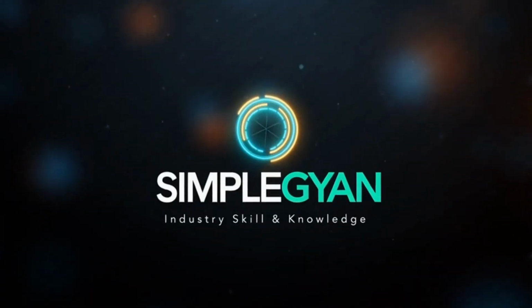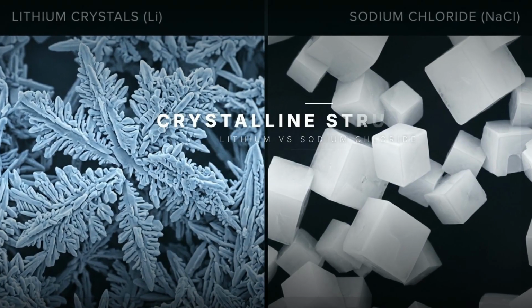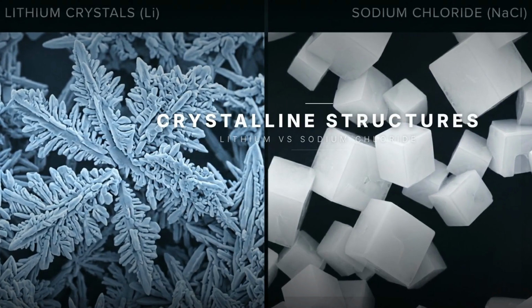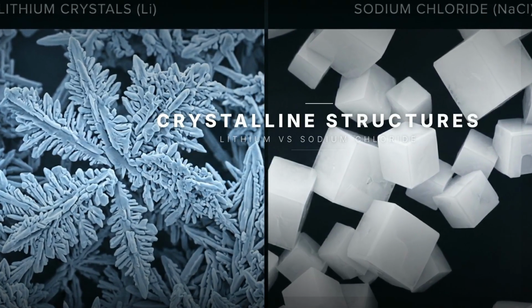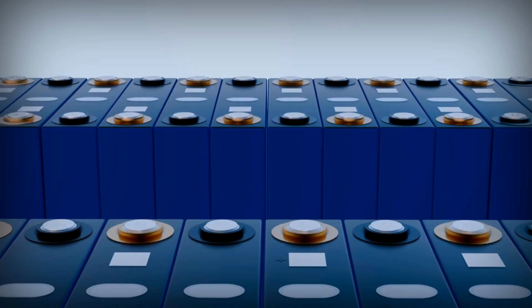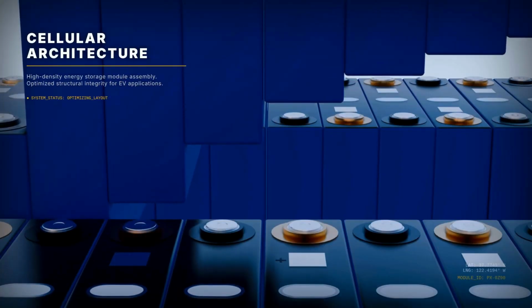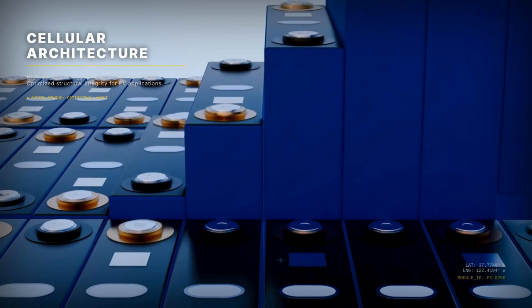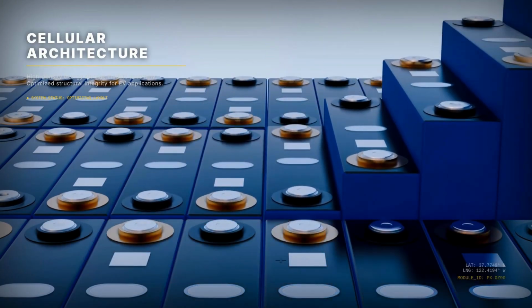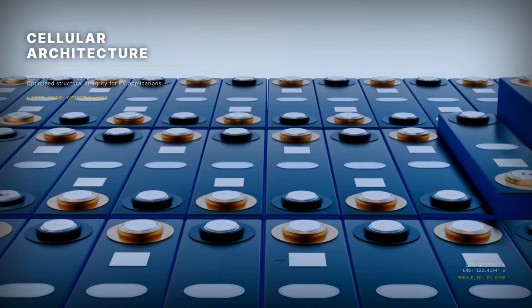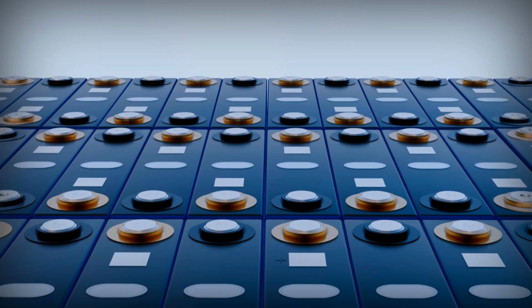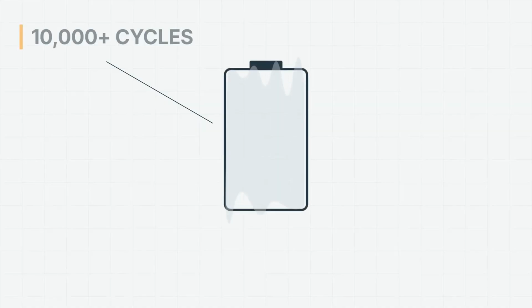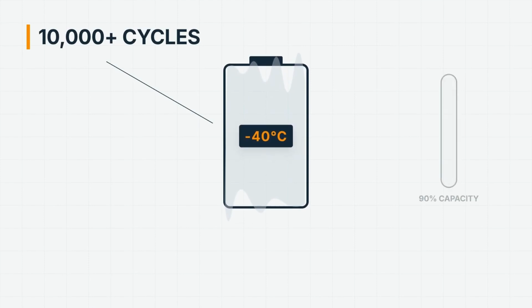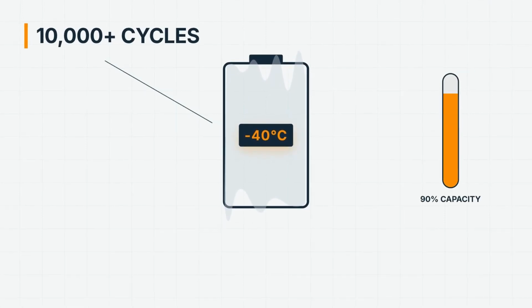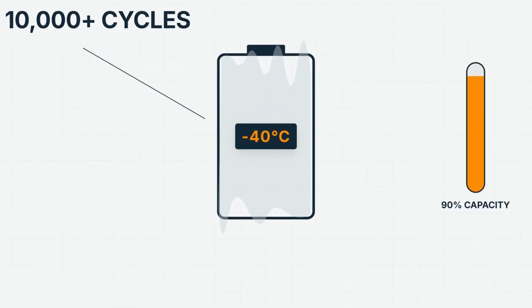This is Simple Gyan. What if I told you that the next big battery revolution may not come from rare lithium mines, but from the same element found in ordinary table salt? A sodium-ion battery does not use lithium, cobalt, or nickel in many designs, and some latest sodium-ion cells can reach around 175 watt-hours per kilogram with strong cold weather performance. CATL has claimed its Naxtra sodium-ion battery can retain about 90% capacity at -40 degrees Celsius and achieve over 10,000 cycles in its announced design.